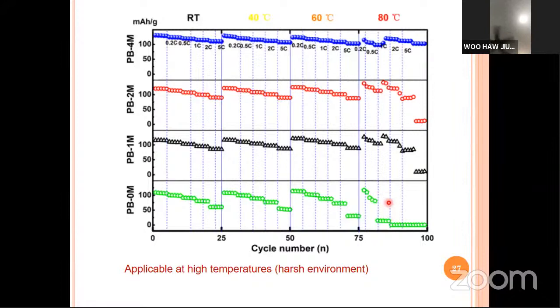As we improve the Prussian blue sodium content from PB-1M to 2M and 4M, we find that at elevated temperature, sodium-rich Prussian blue can actually perform as a sodium-ion battery much better than the PB-0M. Okay. Now look at this, the 5C rating. It still shows us quite good performance, close to 100 milliampere hour per gram.